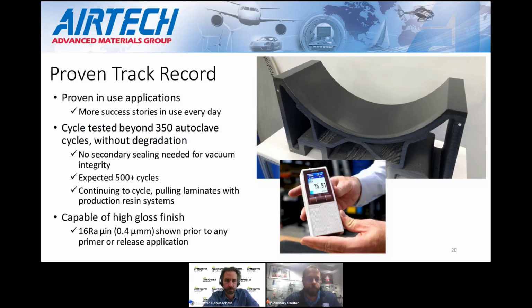So again, proving them out in use. You can see the cycle test tool that's there. Like I said, we are past 350 autoclave cycles now. We're not seeing any signs of failure. And again, no secondary sealing is needed for that vacuum integrity. We do expect it to go past 500 cycles. We are continuing to cycle that and pull laminates, and then again, publish those results.